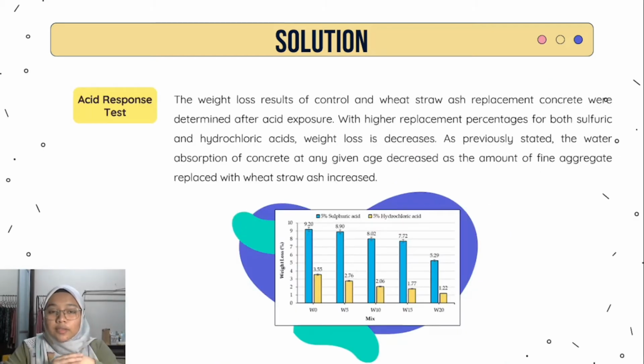For the last testing result, which is the acid response test, with a higher replacement percentage, in sulfuric and hydrochloric acid, weight loss is decreased. As I previously stated, the water absorption of concrete at any given age decreased as the amount of the fine aggregate replaced with the WSA increased.